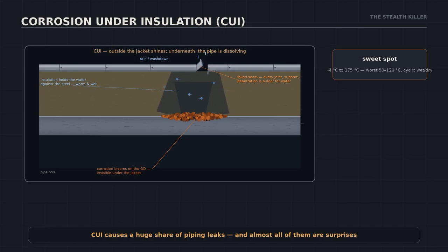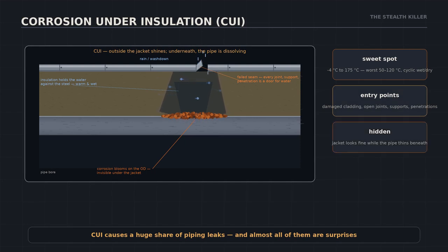And now the stealth killer, corrosion under insulation, CUI. The recipe: water gets past damaged cladding or open joints, the insulation holds it against the pipe like a warm sponge, and the pipe corrodes on the outside, invisibly, because the jacket looks perfect. The danger zone is roughly -4 to 175 degrees Celsius, worst between 50 and 120, and especially on cyclic, wet-dry service. Carbon steel rusts, stainless steel can suffer chloride stress cracking under the same wet insulation. CUI causes an outsized share of piping leaks, and nearly all of them are complete surprises.